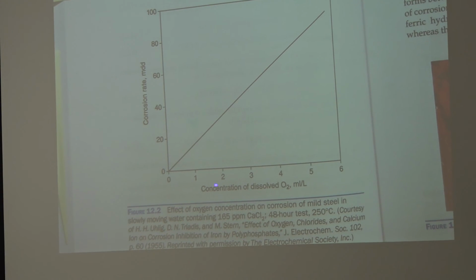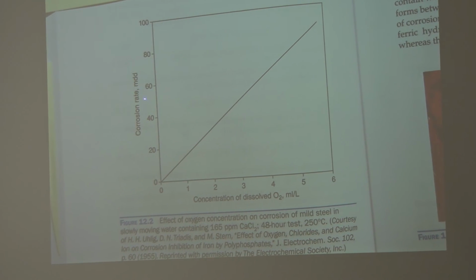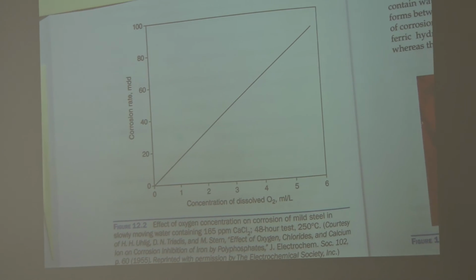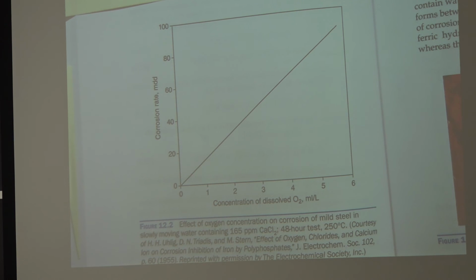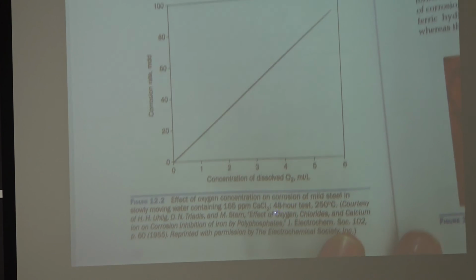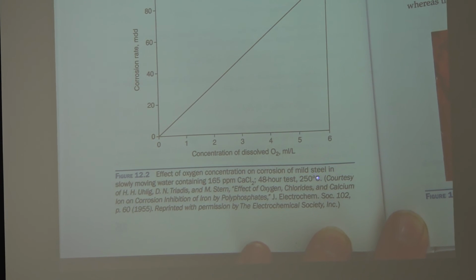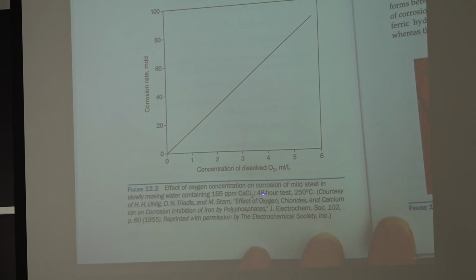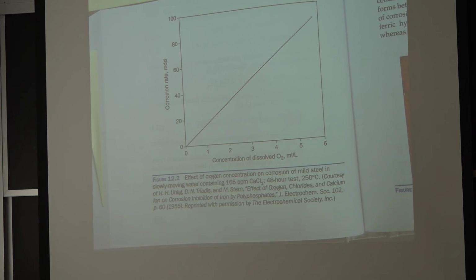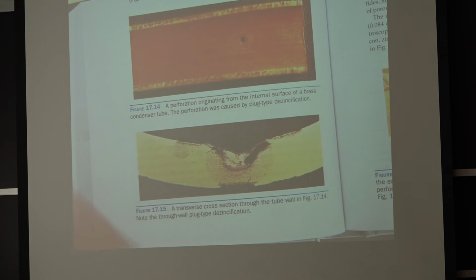Concentration of dissolved oxygen versus corrosion rate in milligrams per square decimeter per day. Don't ask me why these people use these units, but that's what they used back in the 1930s. Effective oxygen concentration on corrosion of mild steel in slowly moving water containing 165 parts per million chloride. And pretty good correlation: you need oxygen to corrode.